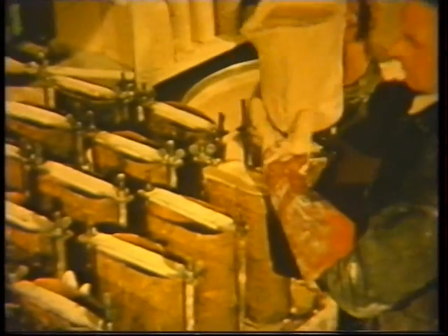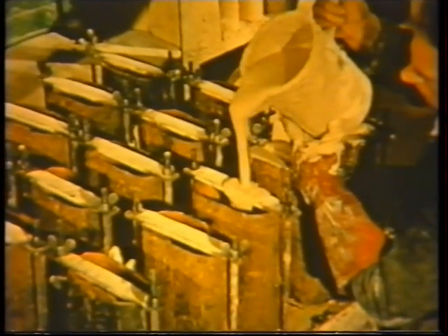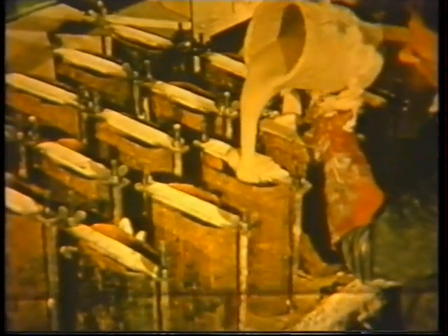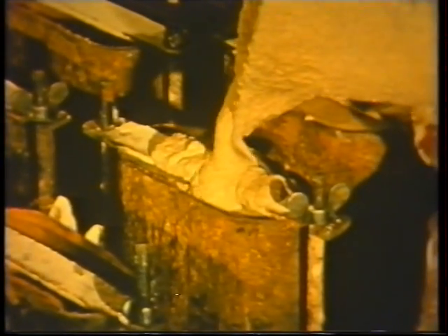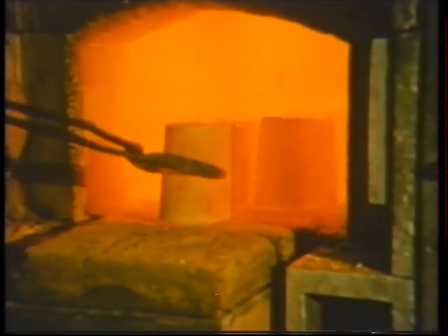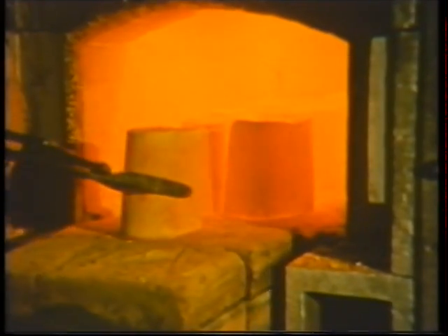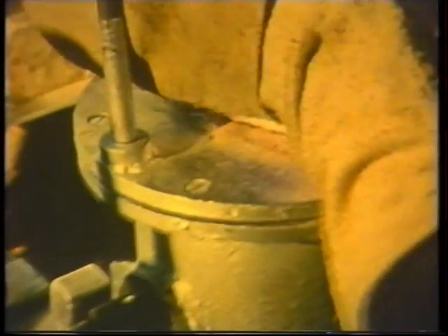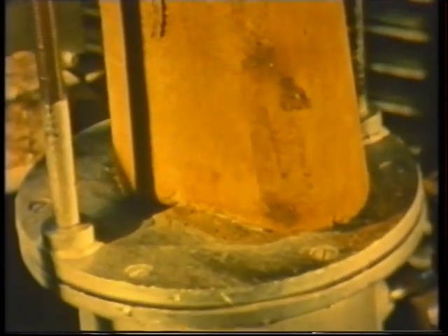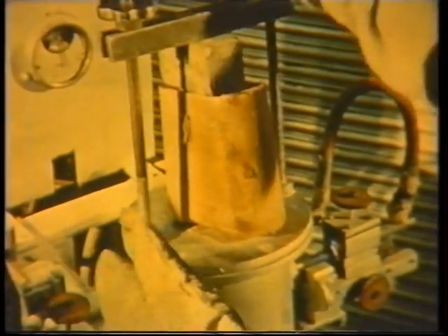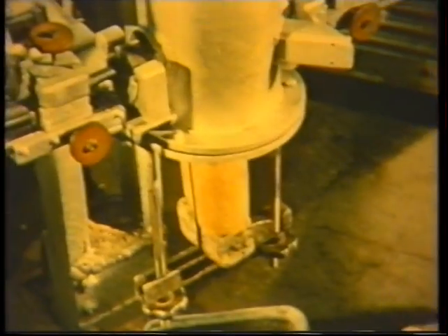The assembly is then mounted and bonded with investing refractory, which is allowed to solidify and dry out. The mold is then heated to low temperature to remove the wax, and then preheated to 1050 degrees centigrade, ready for casting. Steel is melted in small electric furnaces, the hot mold fixed over the furnace aperture, and the whole assembly turned to allow the steel to flow into the mold.